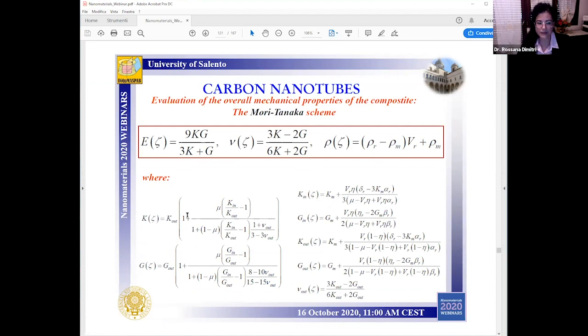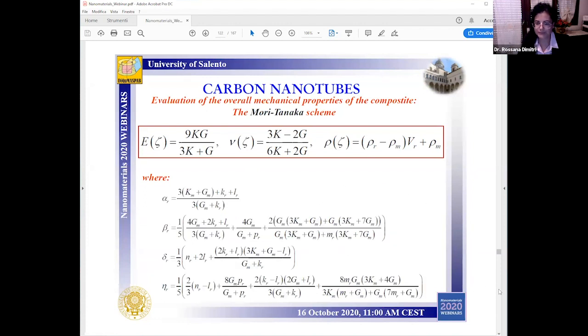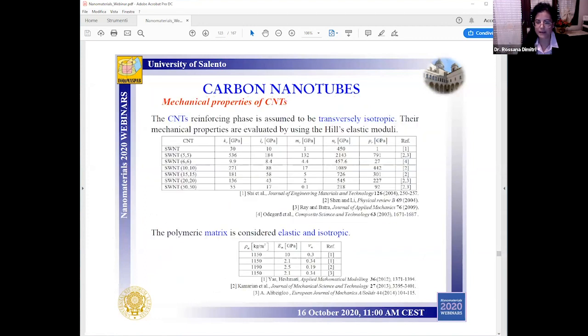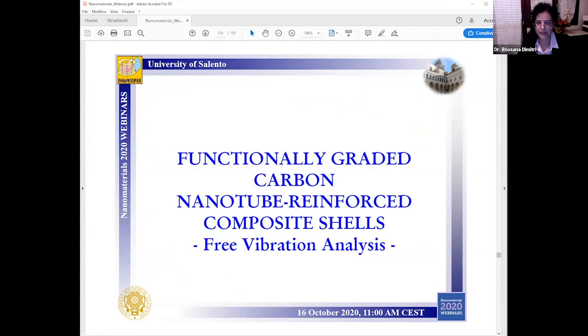See, for example, the effective bulk modulus and shear modulus for the composite layer defined by means of the properties of the inclusions and hybrid matrix. And since the composite ply is isotropic, the Young modulus, the Poisson ratio, and the density are evaluated, as you can see here, where we introduce also these further quantities. And here are some mechanical properties of carbon nanotubes and the polymeric matrix found in the literature, which we have referred to in our numerical analysis and numerical applications.